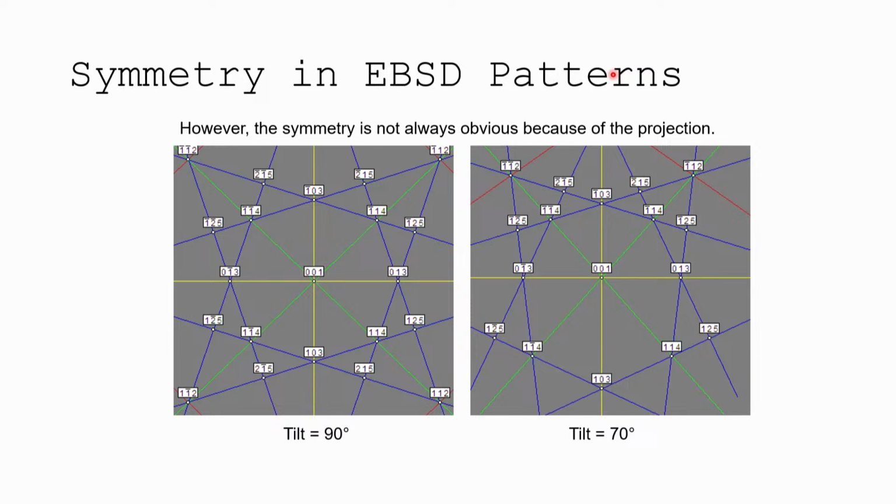If we just plot longitude and latitude as squares, then Greenland, which is north of the US, of course, looks really big, right? The island Greenland all of a sudden looks really big just because of how the projection's done. So you get distortions because of the projection. So we have this spherical entity of the pattern coming out in different directions radially, and we're projecting it onto a flat surface. It's called a gnomonic projection. So we have some distortion, and we have a tilt of the crystal.